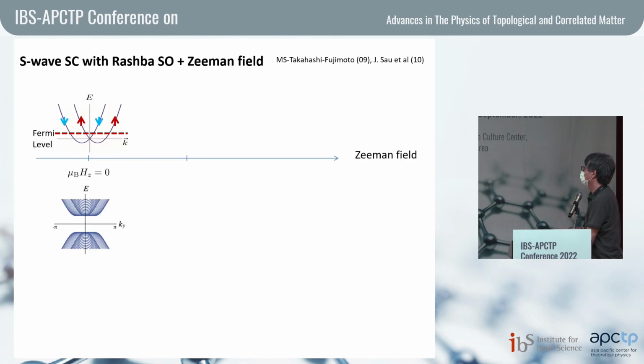And we also have another example. Here I consider the s-wave Rashba superconductor with a Zeeman field. The presence of the chiral Majorana fermion in this case was first established in this paper in the context of cold atomic systems. And later, they and collaborators naturally generalized this idea to semiconductor systems. So anyway, in the absence of the Zeeman field, we have this kind of band structure in the normal state. Now we are considering the Rashba spin-orbit interaction, so we have a spin-split band structure like this one. If you consider the Fermi level here, we have a smaller Fermi surface and a larger Fermi surface. So we have two non-spin degenerate Fermi surfaces.